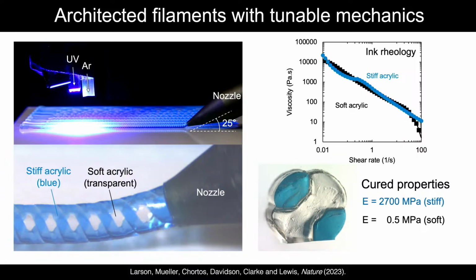And so one of the examples that we had in this paper, we did dielectric elastomer actuators, which I won't talk about, but Natalie was really interested in these, what she called springy filaments and lattices. I call them architected, but same idea. You can see that during the printing process, we're UV curing this material on the fly, and the nozzle in this case is tilted. So this is really how it comes out.